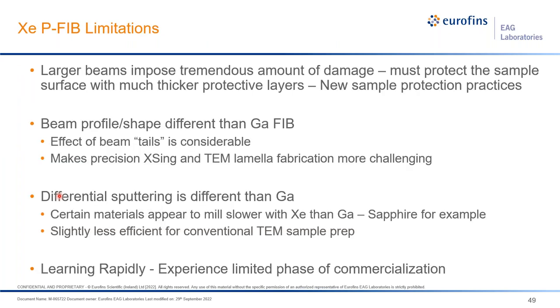So with that, we've got to think about a few of the limitations for PFIB and make sure that we're aware of these things. These very large beams impose a tremendous amount of damage on the sample surface. So we have to protect the sample surface with much thicker protective layers than traditional gallium FIB. And this is leading to new sample protection practices and development of new layers for these situations.